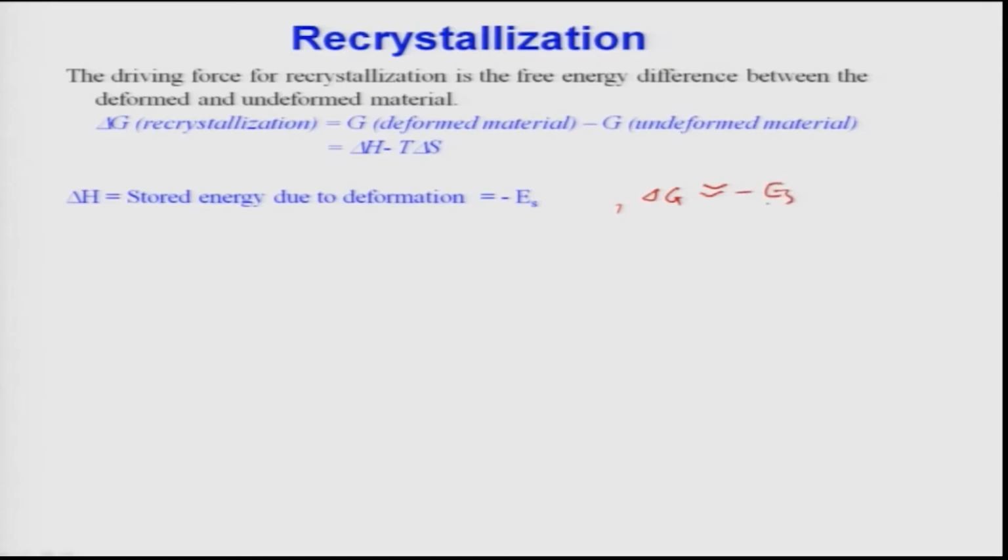And to give you a value which is given in this book, the value of E_S for the silver gold alloy, 70% silver and 30% gold, is about 0.33 kilojoule per gram atom. Okay, so that's the value now available. Now this is the important aspect.